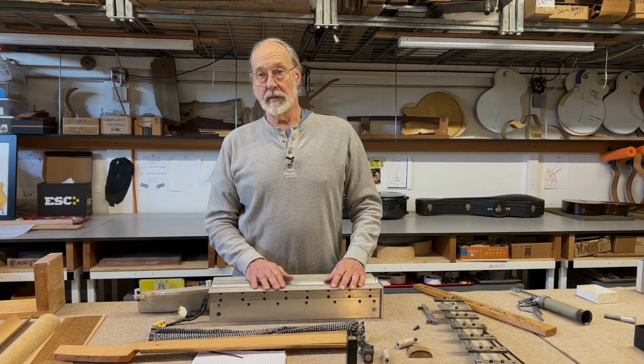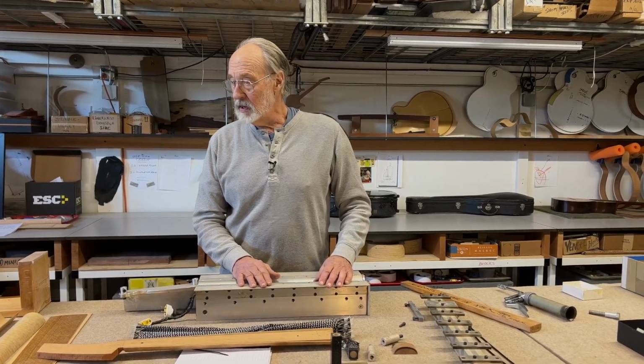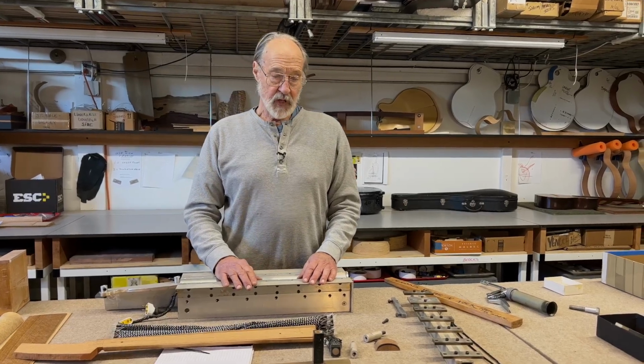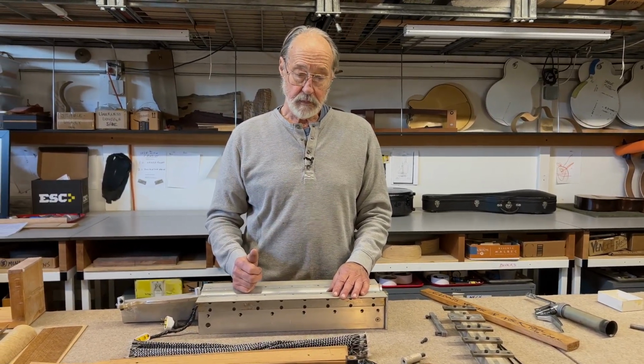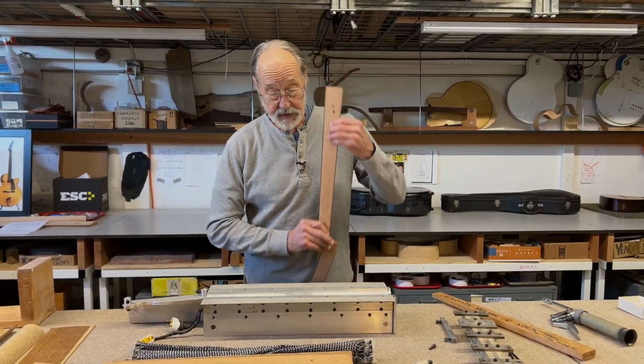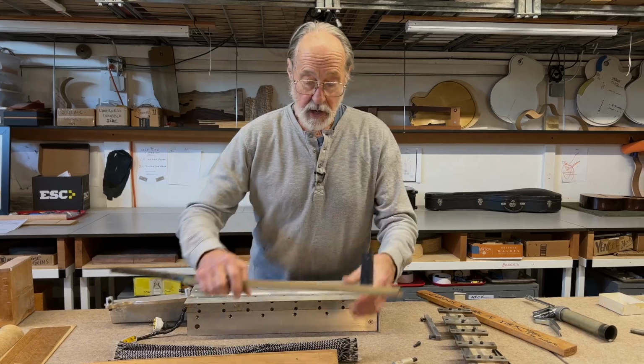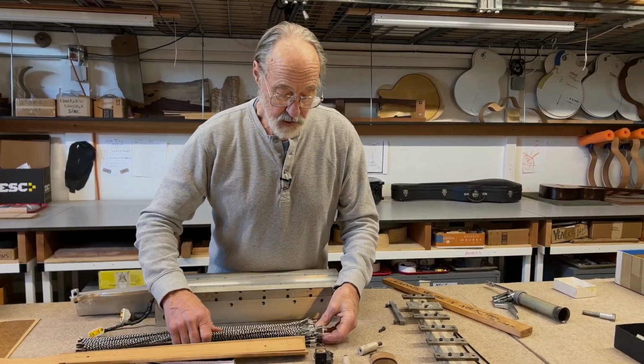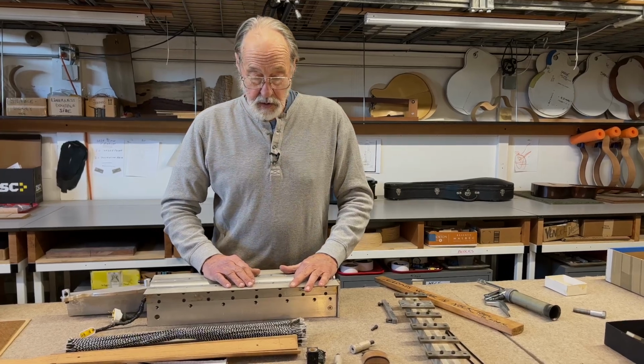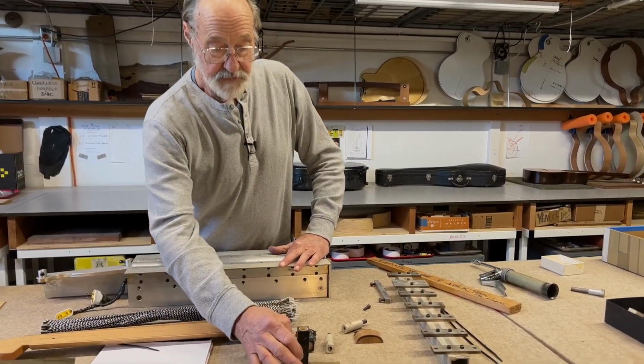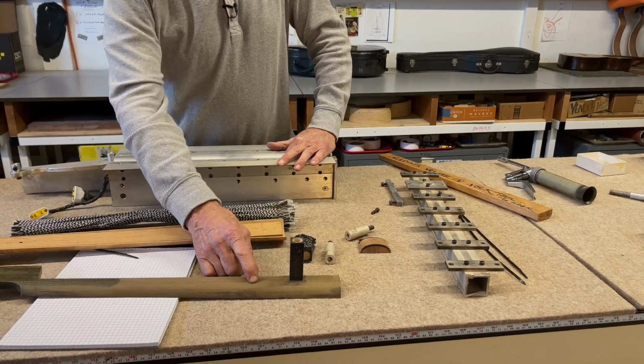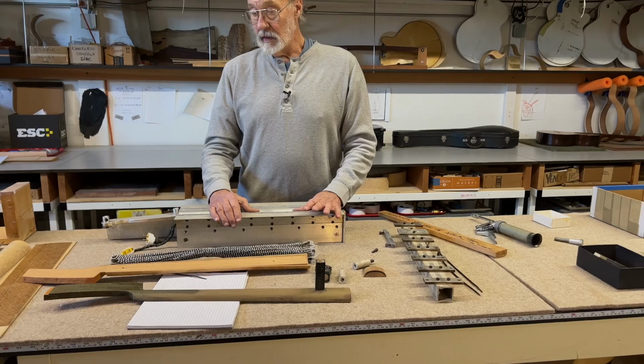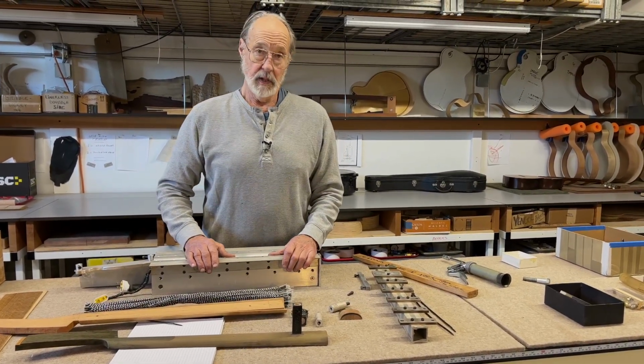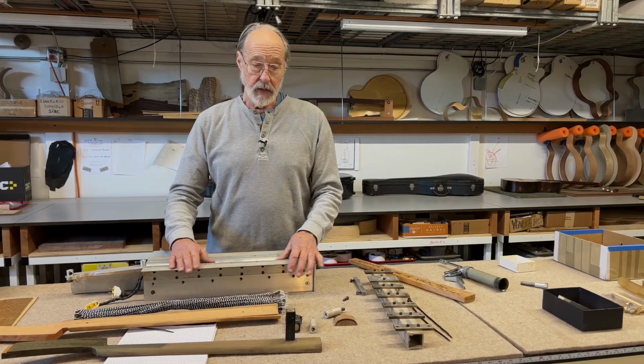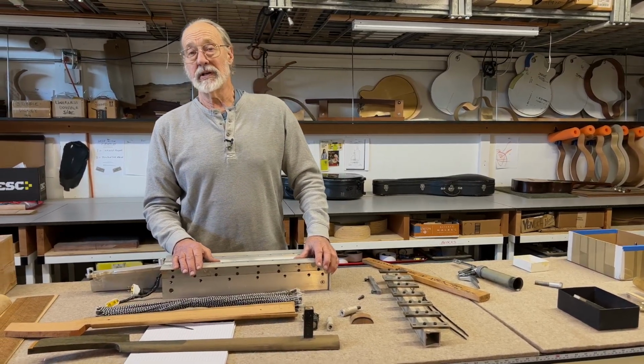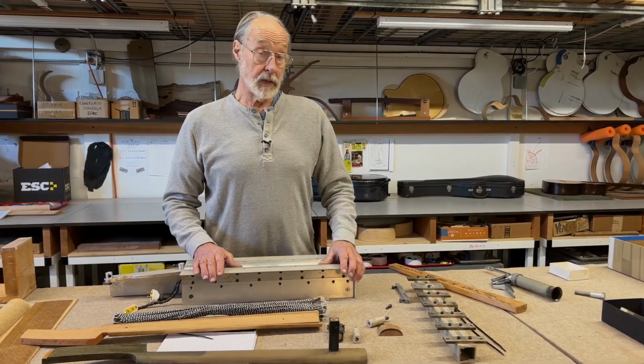And I've learned quite a lot about doing this in the last 18 years I've been up to it. What I will say is that it creates a neck that has a very high resonant frequency, and it's very, very stiff. This is a tremendous amount of carbon fiber to put in a neck, and I get a huge amount of rigidity in the neck joint. This is just massively stiff connection from this pin to the neck structure. What that enables the neck to do is to transmit a great deal more of the energy than a regular neck. And it means that there's lower energy losses, so it adds some power to the guitar.